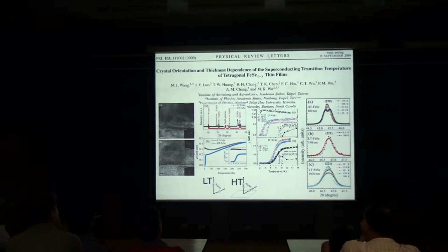This is a little complicated graph. We're making the nice epitaxial film, and we demonstrate that, because of the pinning with the substrate somewhat, you can make it superconducting, like this blue curve shows, or non-superconducting, depending on the process and the material. And for the non-superconducting one, we did a very careful low temperature structure